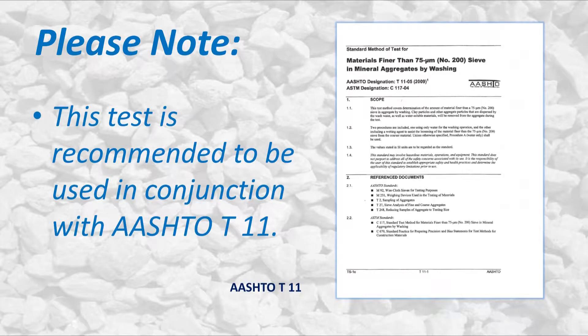Please note the following: accurate determination of material passing the number 200 sieve cannot be made with this test alone. This test is recommended to be used in conjunction with AASHTO T11 to determine the amount of material finer than the number 200 or 75 micrometer sieve.